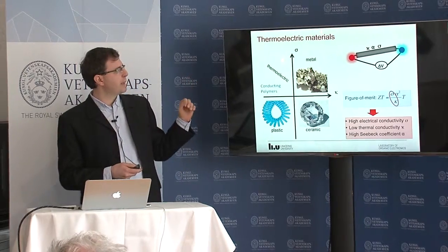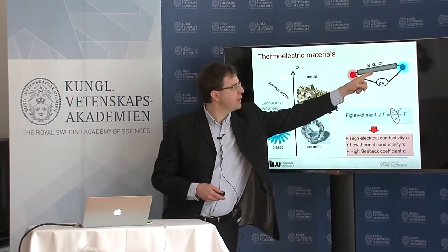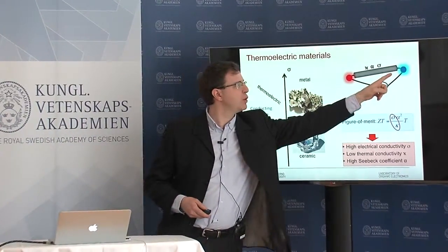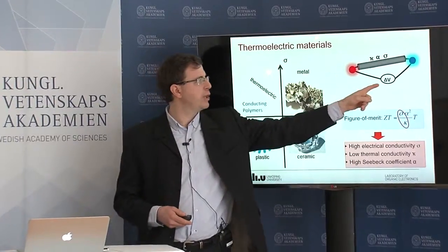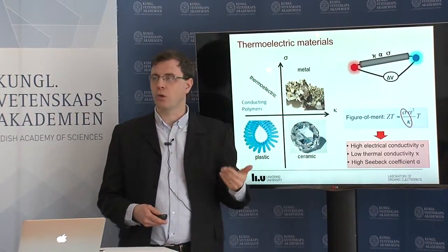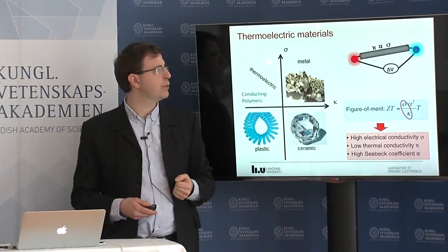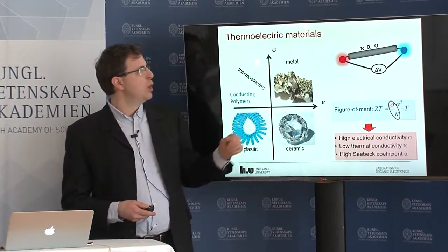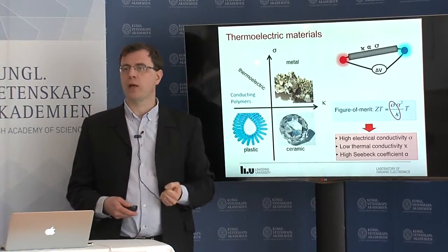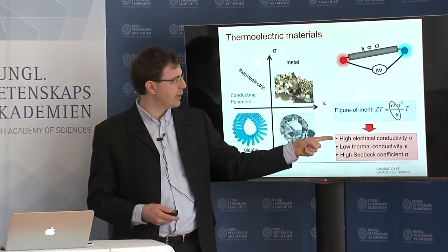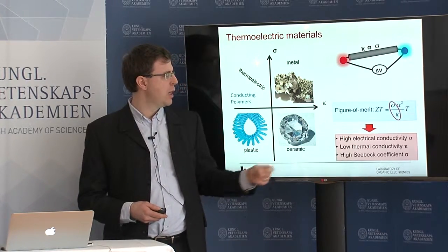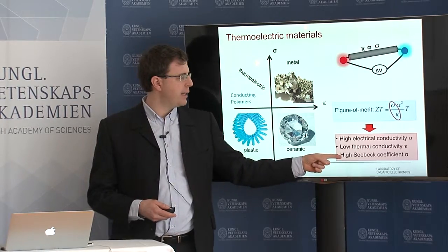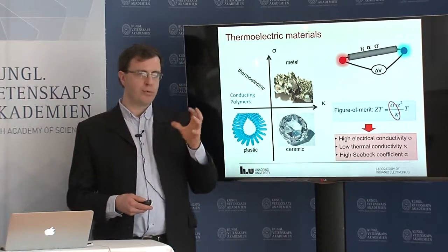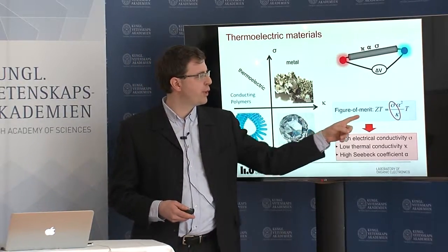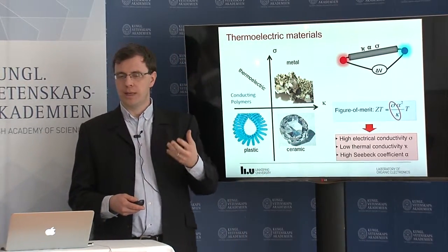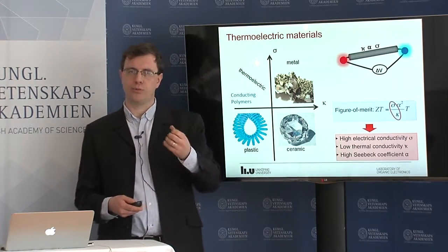So what are thermoelectric materials? How it works is that if you have these materials and you put that between a hot side and a cold side, it actually generates a voltage. And since the material is an electrical conductor, it actually also produces an electrical current and electrical power. So what kind of properties would we like to have for thermoelectric materials? It's gathered like this. We want to have a high electrical conductivity, a low thermal conductivity, and a high Seebeck coefficient. So those properties are gathered together in what is called the figure of merit, ZT, which actually tells about the efficiency of the conversion process.